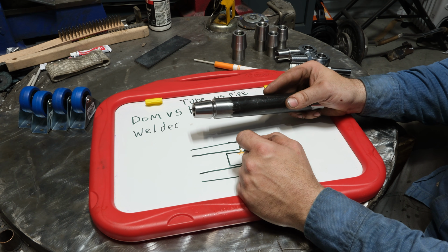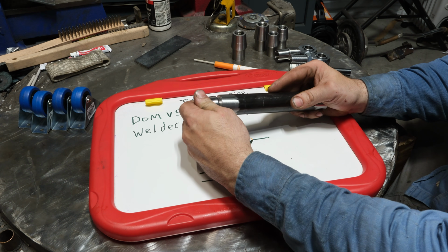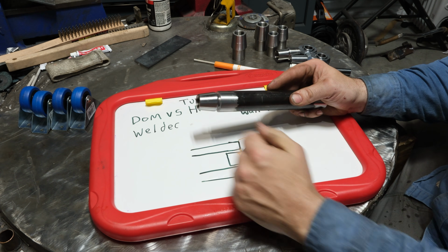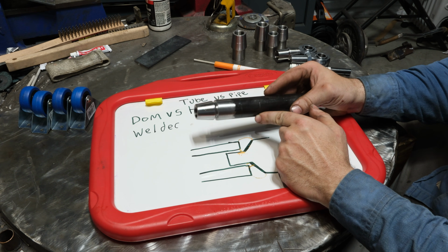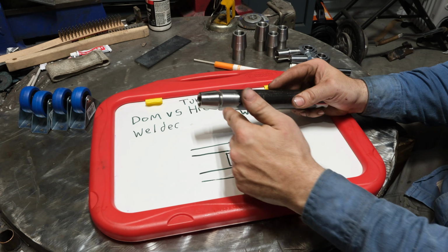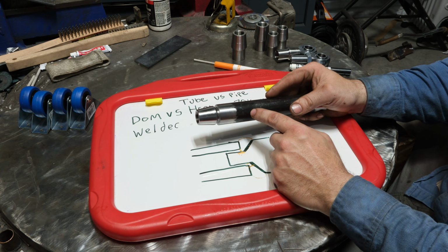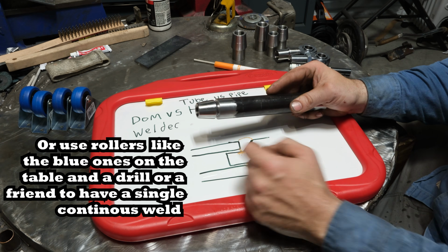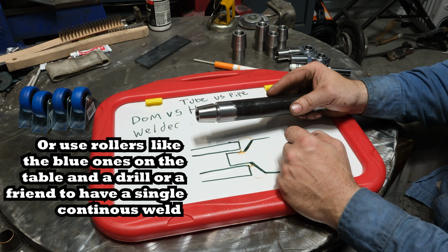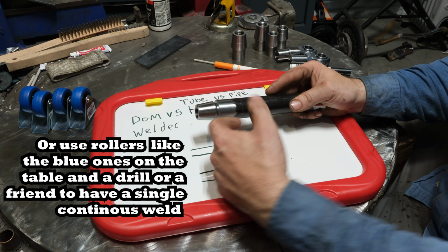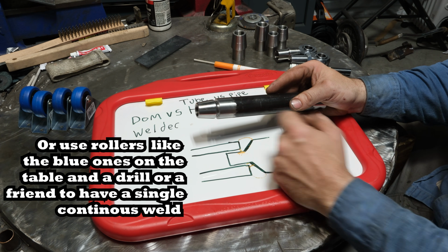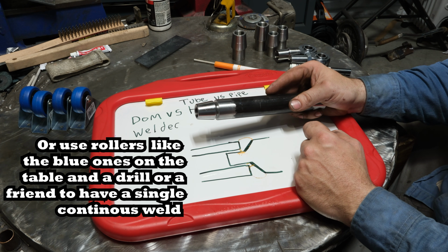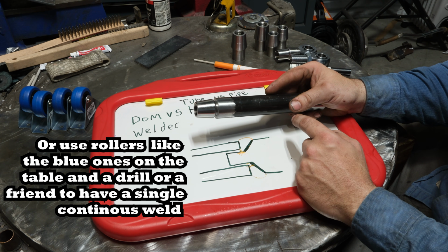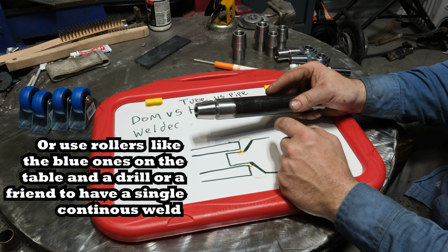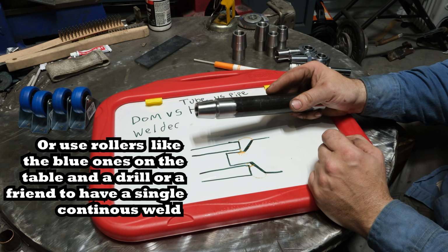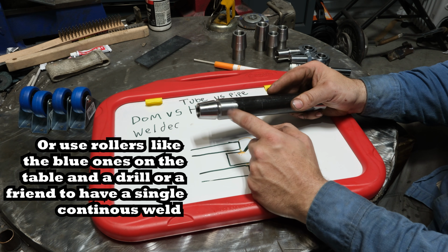So my recommendation is set it where you want it, start welding, and try and weld this in 2 steps, so meaning one whole side, rotate it the other whole side, or do it in 3 steps. So 3 times you start and stop. Do not weld these by tack welding with MIG or stick, so just a bunch of tacks. Don't run cold settings on these, that's a huge mistake. Run appropriate settings and try and do it in thirds. And do not put tack welds and weld over the tacks.